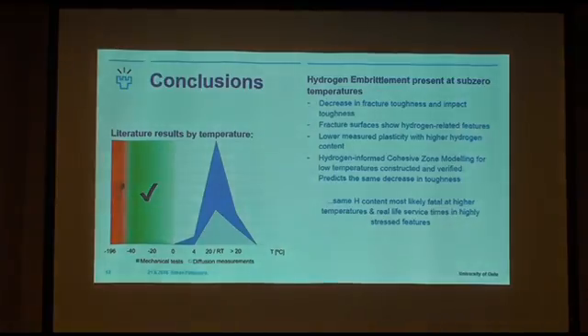So the conclusions are that yes, we do have hydrogen embrittlement present also at sub-zero temperatures, and that is backed by our findings of decrease in fracture toughness and impact toughness values. Our fracture surfaces show hydrogen-related features, and we get lower measured plasticity with higher hydrogen content. And we have also constructed and verified this hydrogen-informed cohesive zone modelling for these low temperatures and relatively fast strain rates, and it gives good prediction of our toughness properties in the experiments.